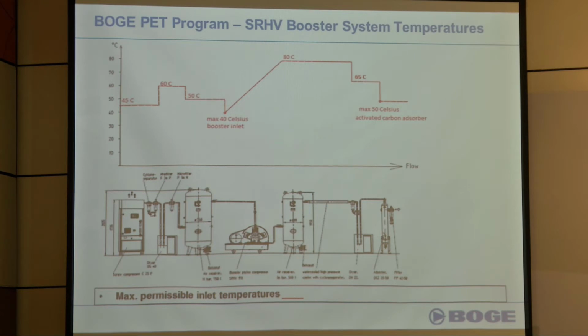So what happens in a high ambient situation of compressed air production, you can see during different stages of compression the temperature rises. At the boosting stages it will rise to 80 degrees. Most of the time 80 degrees is not good for your production or your distribution system. So we can bring down the temperatures using aftercoolers as well as refrigerant cycles, so that it is at a usable temperature level. But of course, when you're blowing PET bottles, you can afford to have a higher temperature, because the bottle preforms are heated during the process anyway.